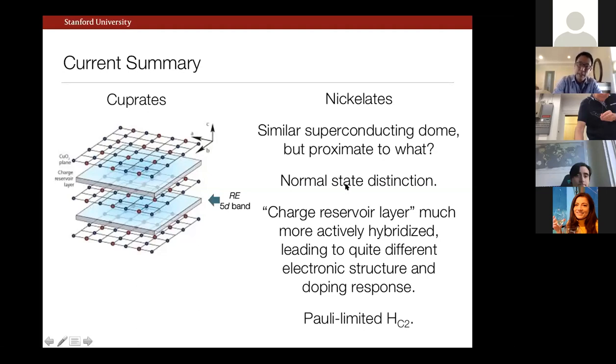The second point I want to emphasize is that despite the similarities of the superconducting dome structure, the normal state is quite distinct from the cuprates, and it may be so in very fundamentally important ways. Again, I go back to this picture: in the cuprates, the notion is that this charge reservoir layer is pretty inert, meaning you can dope, let's say, lanthanum and strontium there, but the charges are transferred to the copper oxide plane. No states near the chemical potential arise from these atoms. So essentially this is a source of disorder, remote ionized impurity scattering, these sorts of things, but otherwise electronically inert.